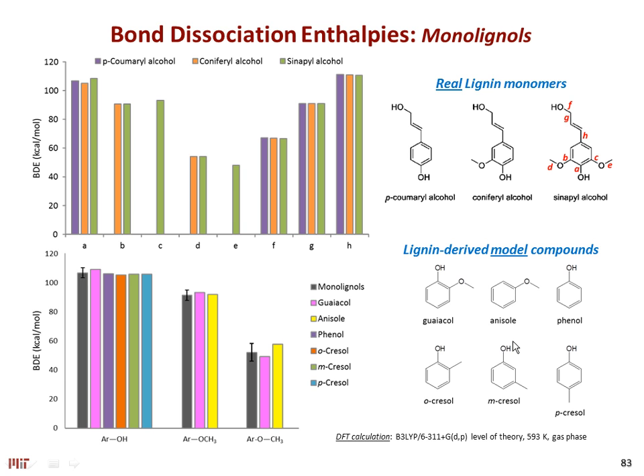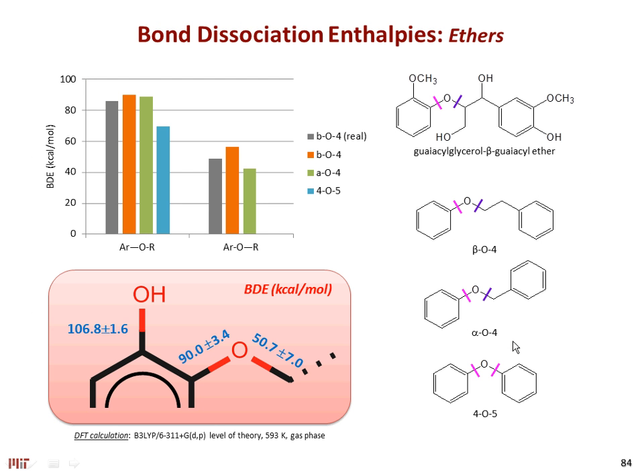So looking at, for example, the lignin fraction, you always have these kinds of building blocks. These are the classic model compounds that people use in the lab. Things like guaiacol or anisole, they have these methoxy groups and hydroxyl groups, and phenol, of course. And when you do the bond energy analysis and start looking at what are the strongest bonds, you see that this methoxy bond is the weakest, this aliphatic bond, and then the aromatic one is stronger, and of course the phenolic bond is the strongest of them all. So what you would expect when you perform some of this HDO chemistry would be to always cleave this bond first, followed by the rest.